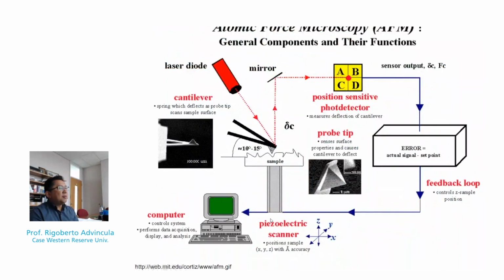So it is best explained by this diagram showing that AFM is essentially a rastering technique with a piezoelectric element so that you can have an XY movement while you're trying to maintain that voltage or that surface force, and there are many ways to configure this experiment. Ultimately, the image or the digital image is derived from the deflection of this cantilever tip with the impinging laser light as detected by a position-sensitive photodetector as shown here.